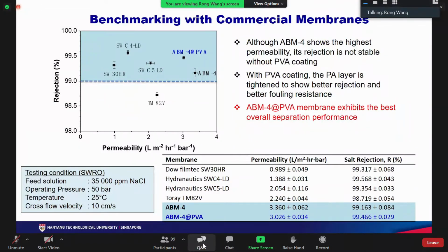We also compare the performance of our newly developed aquaporin-based SWRO membranes with commercial membranes. You can see here, our membranes are listed here: the X axis is water permeability, and Y is the rejection. All the membranes were tested in the lab under the same condition. This is for a fair comparison. So you can see our aquaporin-based membranes with PVA coating exhibit the best overall performance and are much better than the commercial membranes. You can see the result here.